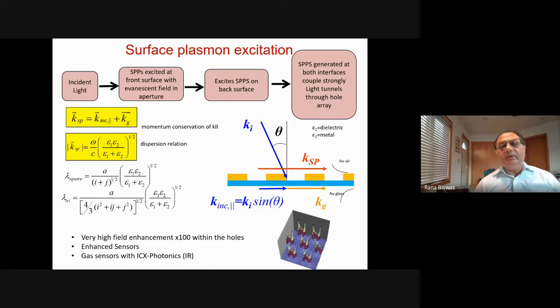So just the basic mechanism of this, it's now quite well known that the incident light comes in, it excites the surface plasmons at the front surface, and it creates evanescent field within the aperture. So this evanescent field excites the surface plasmons now at the back surface. So you have two surface plasmons generated at both interfaces. They couple strongly, and light tunnels through this hole array.